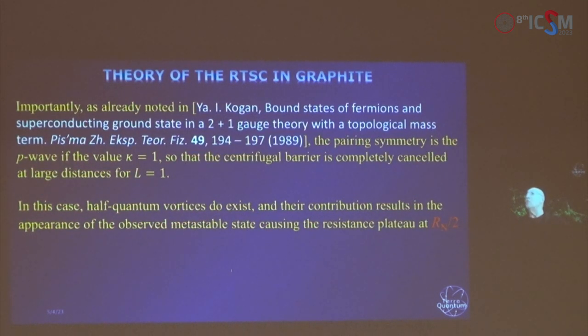And the last notion which we can make is that we consider more carefully the model for the electrons which appear in the wrinkle. We immediately find that those are P waves there, and therefore, in this case, half quantum vortices do exist, and their contribution into observed resistance behavior immediately results in the appearance of the observed metastable state causing the resistance plateau at resistance by half, just because these vortices which contribute to this effect are not full quanta but half quantum vortices. So this completely explains our experimental observation.